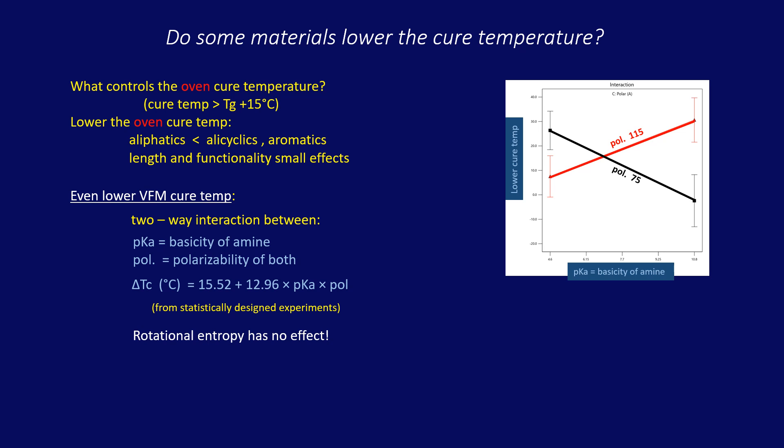There is no effect from rotational entropy. This actually makes sense because in the crowded final cure stages, there isn't as much room for rapid rotation. But microwaves still force the dipoles to move and the reactions to complete.